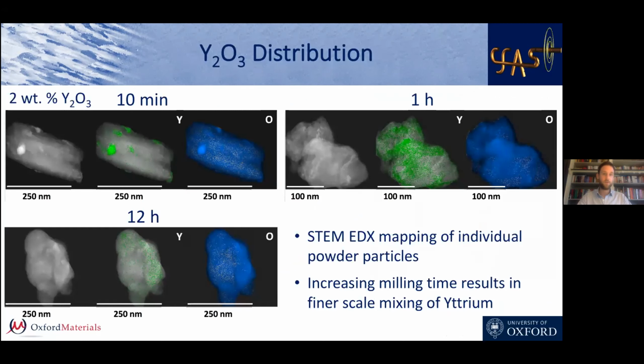The first step was obviously to manufacture the powder. What we did is that we ball mill for different amounts of time, and we realized, so these are some transmission electron microscope images, that if you ball mill only for a short time, the big gray particle is the MgB2 matrix, and then the smaller white ones, that are also green and blue on the yttrium and oxygen maps, represent the yttria particles. And after a very short time, we can still very much see them. They are discrete and embedded or on the surface of the MgB2 powder particles.